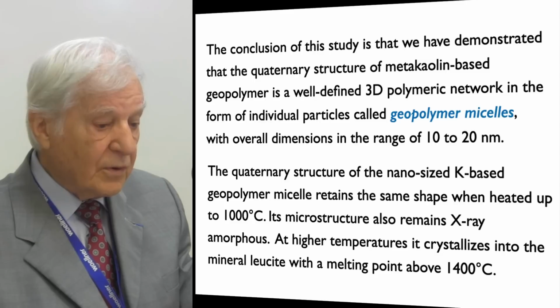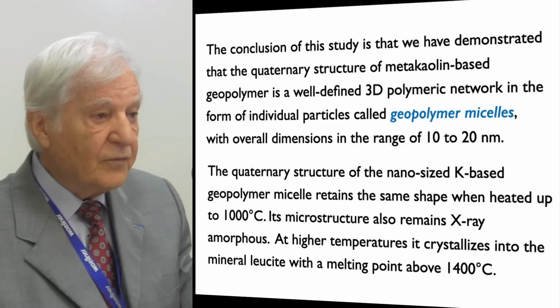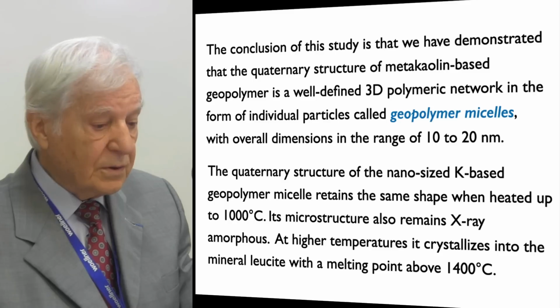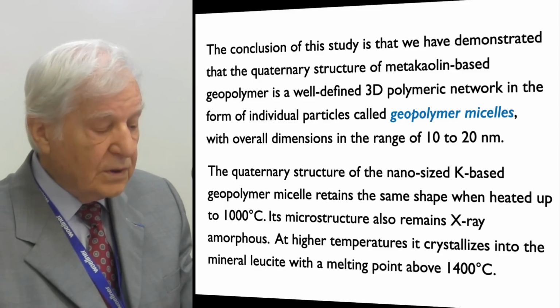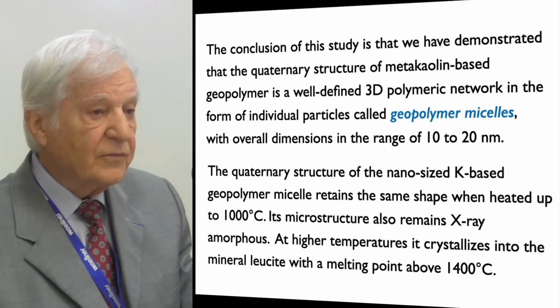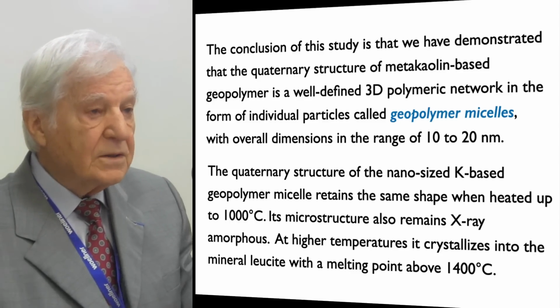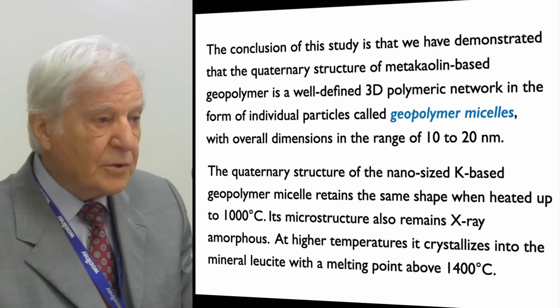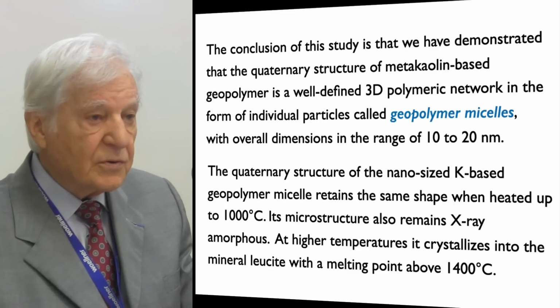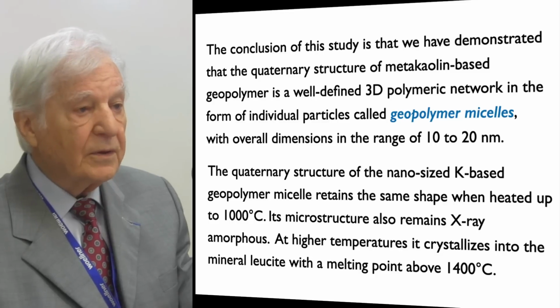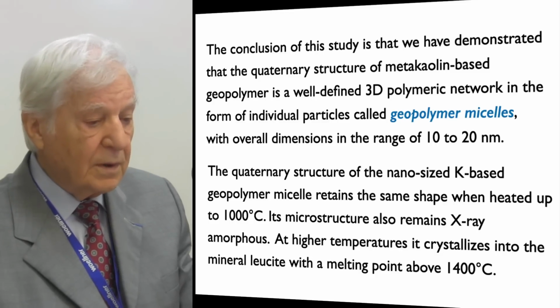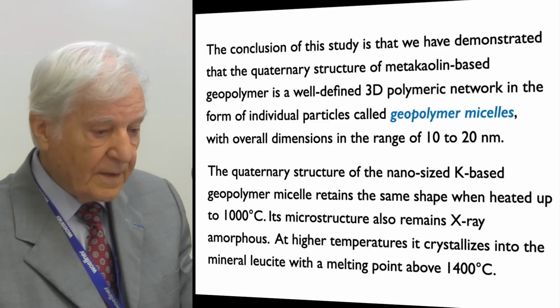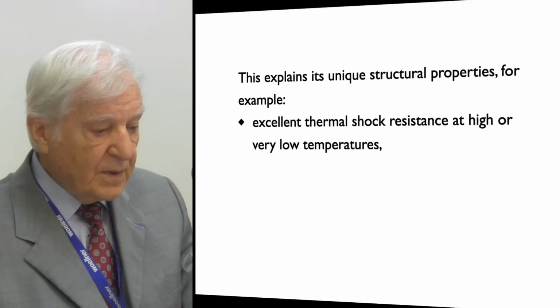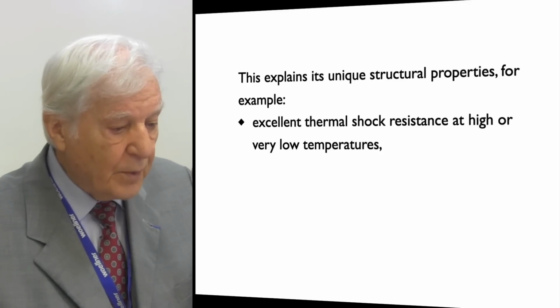Its microstructure also remains X-ray amorphous. At higher temperatures, it crystallizes into the mineral leucite with a melting point above 1400 degrees C. This is a potassium-based geopolymer, not the sodium. The sodium will provide a different structure, but also geopolymer micelles. This explains its unique structural properties.